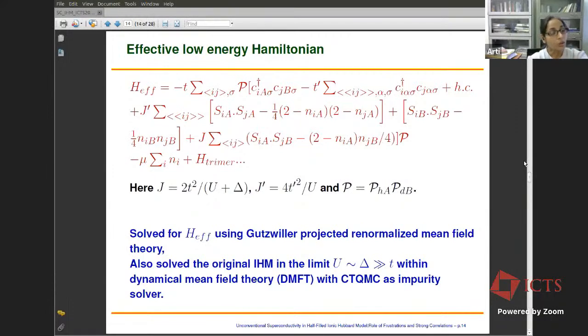So how can one go ahead and solve this effective low energy Hamiltonian? So one thing to notice here is that the projected fermion operators, which can create particles and annihilate particles on A and B sublattices in this strong correlation limit, they do not satisfy the standard Lie algebra of the fermions. So the Wick's theorem doesn't hold, and it's not possible to do any standard perturbation theory in terms of the C tilde and C double tilde operators, which I defined a few slides back. So generally the standard methods available are the numerical methods like variational Monte Carlo, and maybe one can try some DMRG and some other methods.